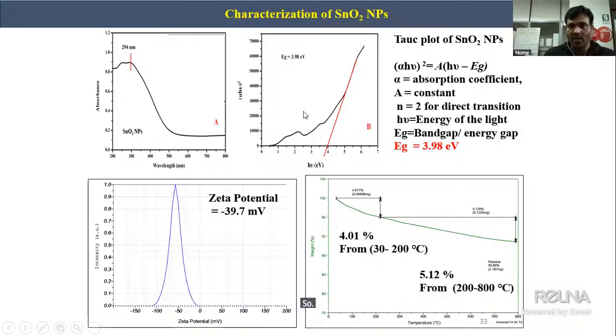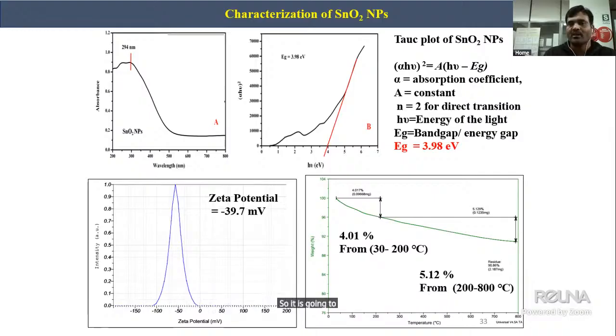Further, the tin oxide nanomaterial is confirmed by UV-visible analysis, and band gap analysis was calculated. UV-visible identifies the formation of the material by its specific absorbance value. Based on the absorbance, each metal has a specific absorbance value, so the material is confirmed. Further, the band gap was calculated by the Tauc plot derivation.